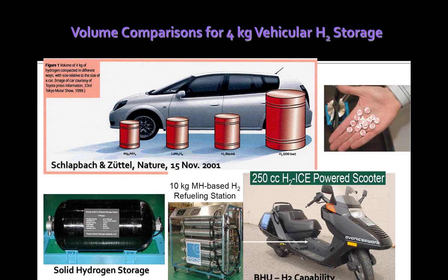For liquid hydrogen, you are cooling the hydrogen first with liquid nitrogen, which is about 77 Kelvin, and then cooling down to liquid hydrogen, which is about 21 Kelvin. So you are freezing and cooling that hydrogen and packing it in a canister. That can only probably be done by space agencies like ISRO or NASA, who can spend billions of dollars or billions of rupees to use liquid hydrogen for space shuttles. The volume is comparatively less, but it's not enough, so you need to go further down.